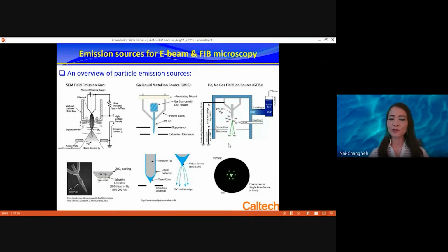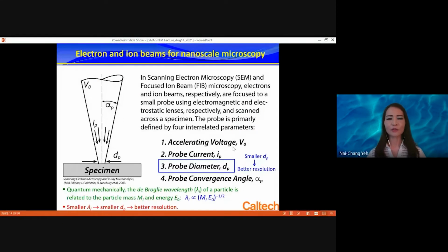And once these particles are extracted, you use different techniques to focus the beams into small dimensions. In scanning electron microscopy, called SEM, or focused ion beam microscopy, called FIB, electrons and ion beams respectively are focused into a small probe. You want to have high resolution so you can image or fabricate small structures. If you have electrons, you use electromagnetic fields to focus the beam. And if you have ions, you use electrostatic, quote unquote, lenses to focus the beams, as if they are optical lenses for photons. The principles are similar. If you use particle-wave duality, it's just that the mechanisms to focus them are different.